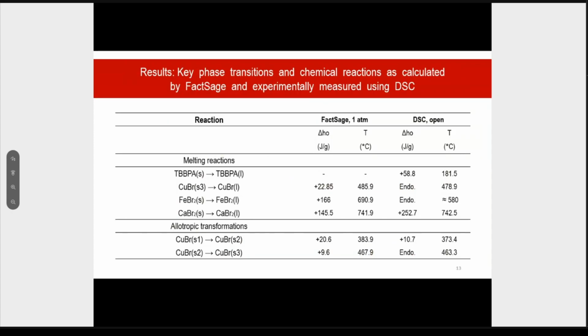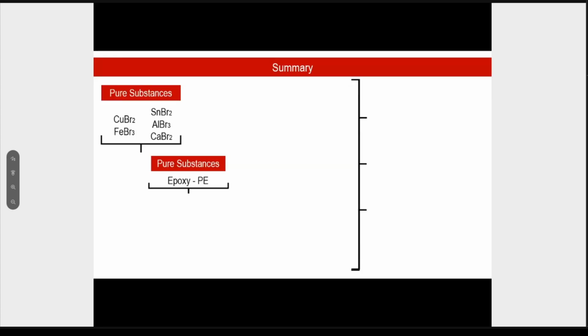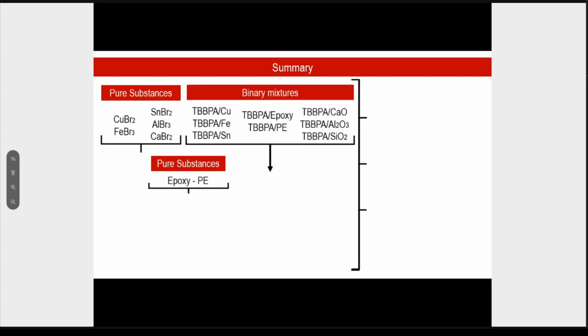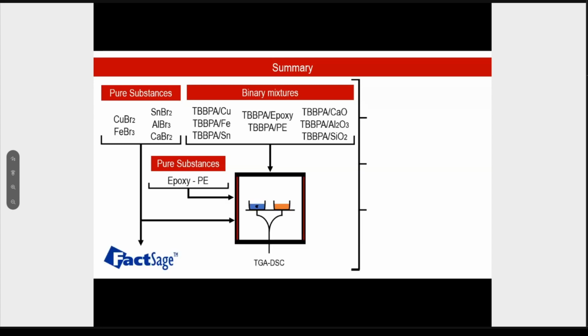So in this way, we were able to test the same method, which we applied, as I mentioned earlier, to different metals, different metal oxides, and also to polymers. We were also able to compare our results with FactSage using DSC to confirm that FactSage can predict what we analyze experimentally using DSC and TGA. To summarize, we started with pure substances like all the brominated metals, epoxy resins, and polyethylene, and also binary mixtures composed of the flame retardant with all the pure metals, the epoxies, polyethylene, and metal oxides. We compared this using TGA, DSC, and also FactSage.